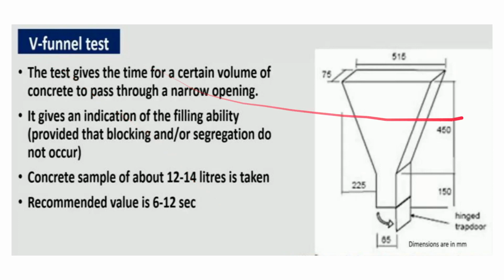As you can see here, it is the specification, the standard dimension of the V funnel. So how to do the V funnel test? The test gives the time for a certain volume of concrete to pass through a narrow opening. This is the narrow opening and we have to fill here. It gives an indication of the filling ability provided that blocking and or segregation do not occur in between. A concrete sample of about 12 to 14 liters is taken and poured, and the recommended value is between 6 to 12 seconds. I mistakenly told it to be 8 to 12. It is between 6 to 12 seconds.